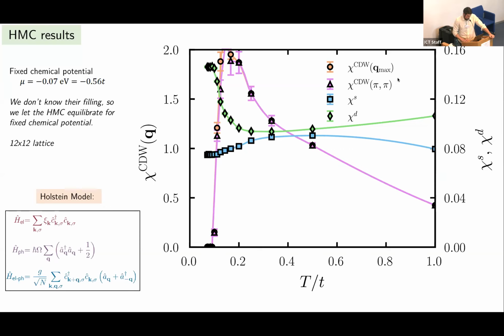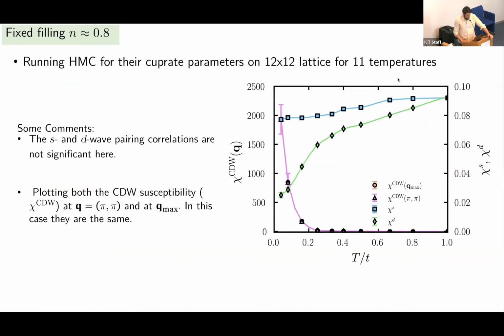And so we looked at their parameters. They didn't specify what the filling was, but more or less we were able to test sort of in the ballpark of where they were. So largely what we find is that if any sort of instability wins, it's going to be a charge density wave for their parameters. And so this is kind of intriguing.